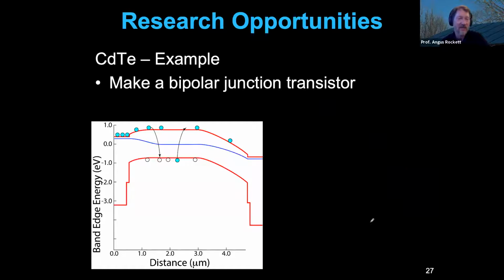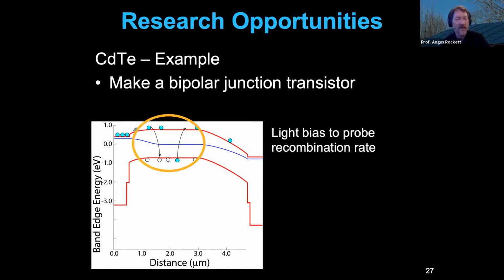And that's to make a bipolar junction transistor out of the device rather than trying to make a solar cell. So a solar cell, you try to make an ohmic contact at the back. A bipolar junction transistor, you try to make a junction on both sides. And the nice thing about a bipolar junction transistor is that you can diagnose a lot of different things with it. So for example, if we run it as a phototransistor and shine light on it, we can diagnose the recombination rate, and we can adjust the photon wavelength to control that recombination rate.